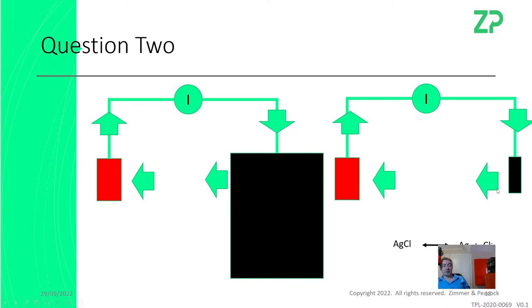And the reason that is the case is because they're actually constructed from silver chloride. And our silver chloride means that we have a large capacity to either accept electrons or give up electrons. The ability for silver chloride to become silver atoms and chloride ions is quite easy. I would use the scientific word facile, it's quite a facile reaction. And so when you make a counter electrode from silver chloride, you have the ability to sink a lot of electrons or give a lot of electrons. And thermodynamically, it can happen relatively easily.